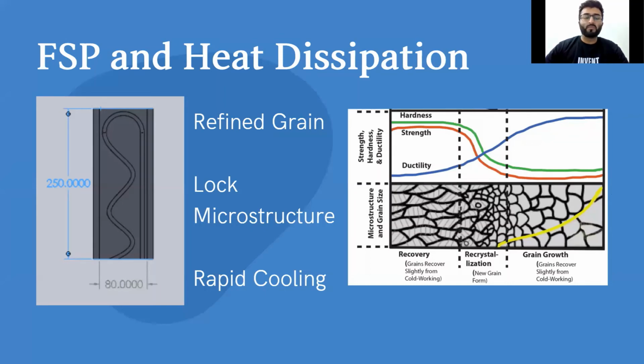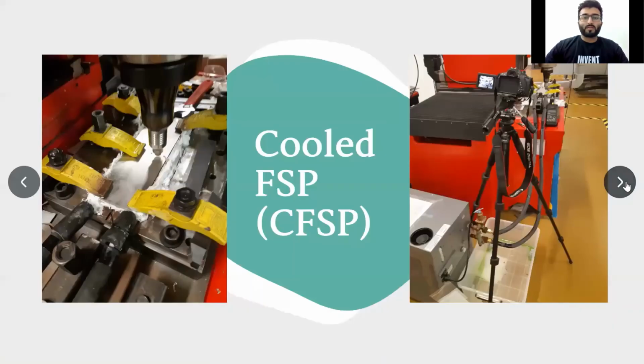In order to do that, we developed a copper heat exchanger to absorb this excess heat while the FSP is underway. This locks the microstructure by effective heat dissipation from the sheet to the coolant, which is initially at -20 degrees Celsius. This shows the cooled FSP setup that we have in the lab. You can see the copper tubings entering the copper heat exchanger, which is located under the FSP sheet.